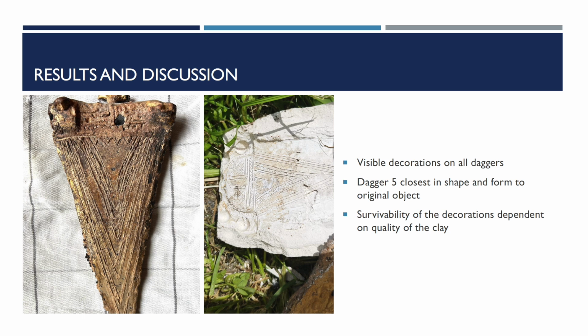The first molds we made were with very coarse clay that was retrieved from just the hills in the Apennine Mountains, while the clay of the mold you can see on the right was a refractory porcelain clay. So the mold survived the casting process quite well.